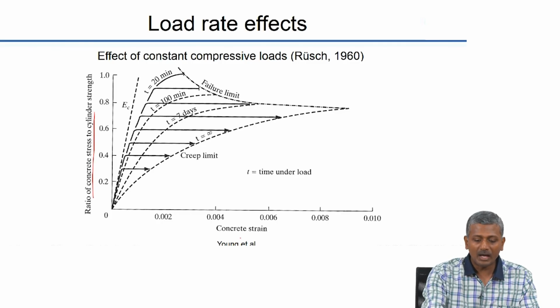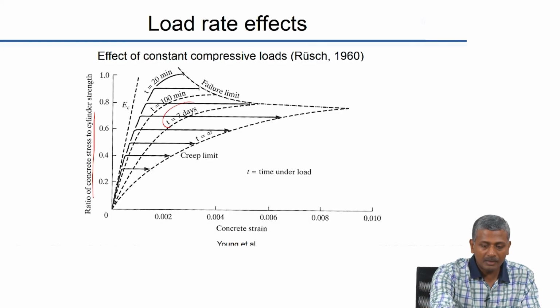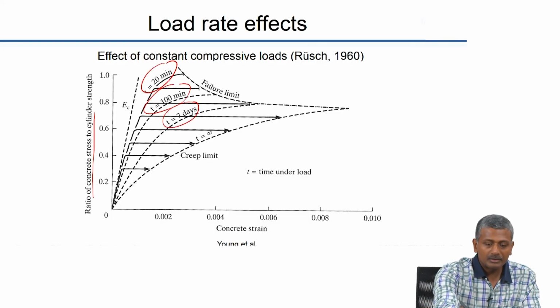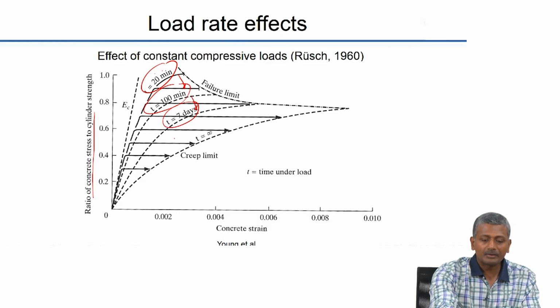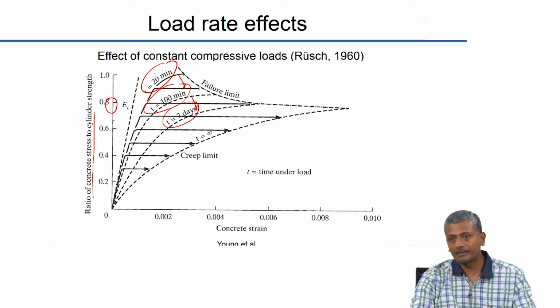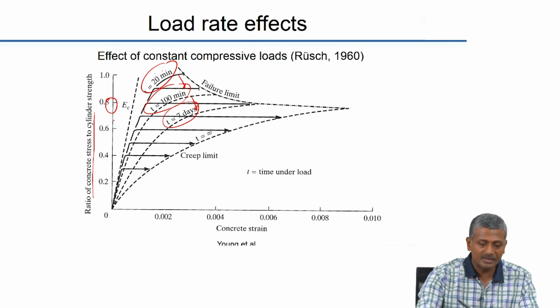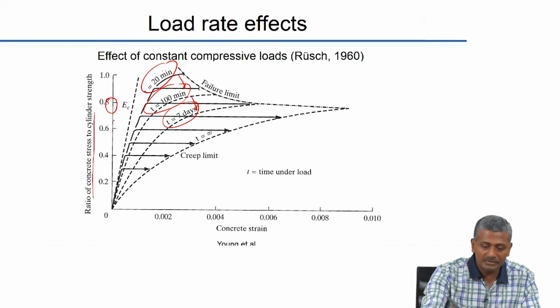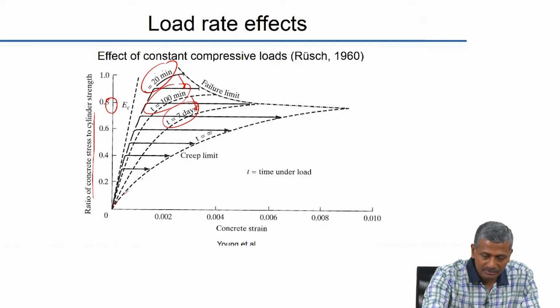When you have a time of application that is very less, for example, when you are at 20 minutes, which is a short term test, when you start increasing the time over which you are applying the load, the overall stress that the concrete can take keeps on reducing, right. Over a long term, the extent of stress that the concrete can take keeps on reducing, and that is basically called the effect of constant compressive loads here. So, what you get out of this is this curve which is called the creep limit.